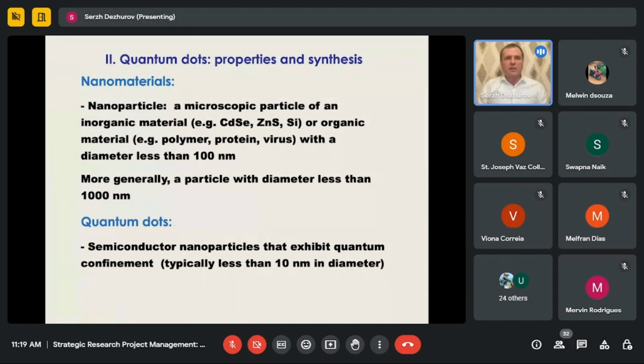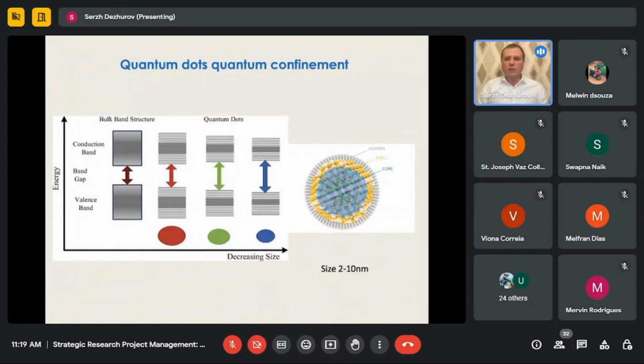The biggest part of these nanoparticles is quantum dots. These are semiconductor nanoparticles that exhibit quantum confinement, and their size is typically less than 10 nanometers in diameter. So what about quantum confinement? Quantum confinement is an interesting effect that appears when your particle has a diameter from 2 to 10 nanometers. At these sizes, we have a special effect.